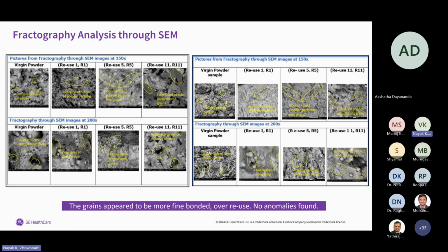So we magnify the particular areas and see that over a period of time the bonding becomes a little bit better, we would say. At some point we saw that properties were also good, and this is because it has been printed multiple times. The sieved powder, we sieve it again and use it for the next batch cycle. So typically the properties change. The grains become a little bit granular, and it becomes more fused. The fusion happens a little bit better, what we have seen.